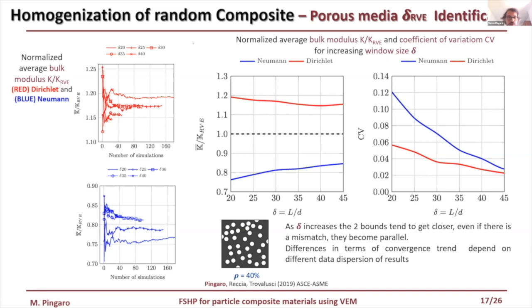In the two left graphs is shown the normalized average bulk modulus, in red the Dirichlet boundary condition, and in blue the Neumann boundary conditions, versus the number of simulations for different window dimensions. And in the right part of the slide is reported the coefficient of variation relative to the bulk modulus at varying the window dimension.